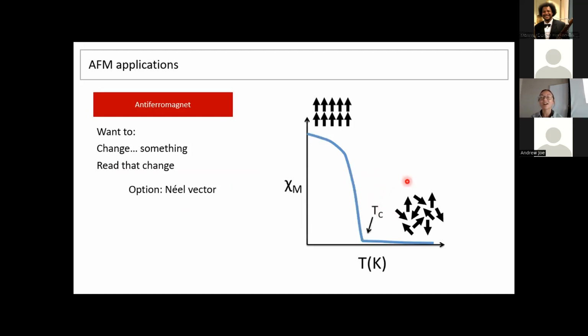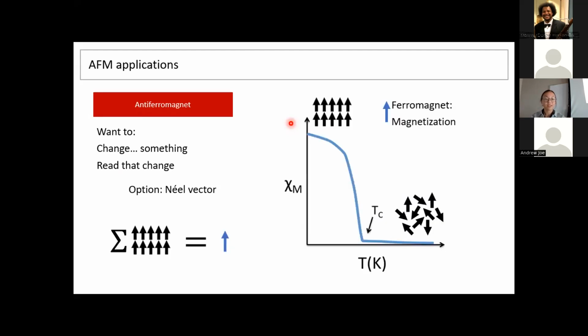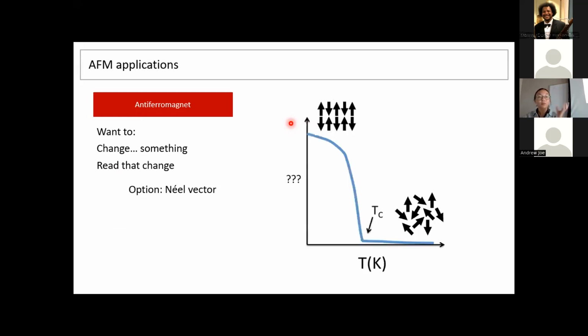So close to the beginning of the talk, I showed you this plot of the magnetic susceptibility as a function of temperature for a ferromagnet. And it has this shape, right, where it's basically 0 when the spins are kind of random and chaotic, and it jumps up when the spins are ordered. So this is the shape of an order parameter. This is the ferromagnetic order parameter. More specifically, magnetization is the ferromagnetic order parameter, where we're summing up all of the spins inside of the material. Now, what can we have for an antiferromagnet that will behave the same way? What can be the antiferromagnetic order parameter? That is the Néel vector.